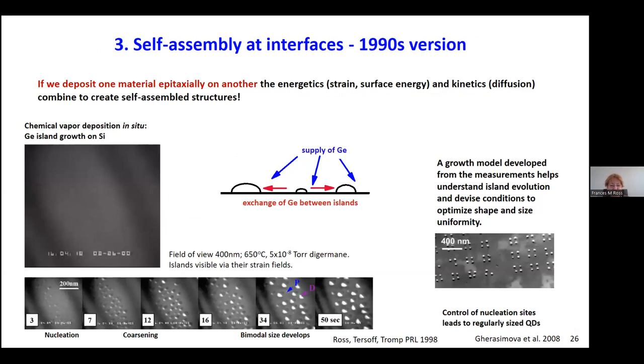The last topic I want to talk about is the use of epitaxy to create self-assembled structures that can be quite complex and have interesting electronic or optical properties. I'm going to firstly show a movie recorded a long time ago, last century, where we're depositing germanium on silicon. It's a similar experimental setup to the nanowire growth, except here we start with a flat silicon surface and heat it to about 650°C, then flow germanium in a reactive gas — digermane. Just like before, the digermane gas lands on the surface, cracks, the hydrogen goes away, and the germanium is left behind to decide what it wants to do.